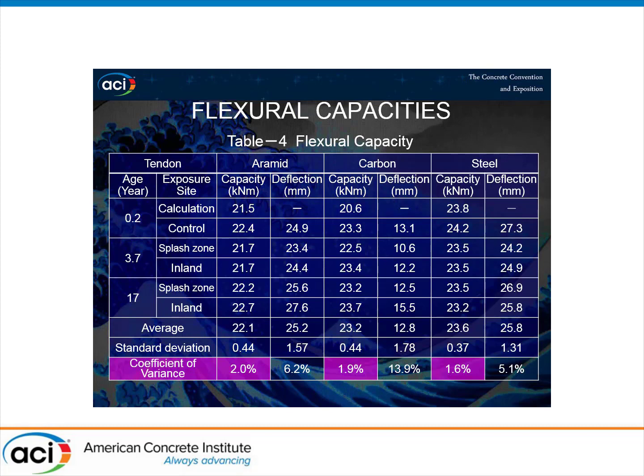To notice the flexural moment capacity, the values have no difference. They had a coefficient of variance less than 2%, and it matches nearly perfectly with the calculation. In other words, aging degradation caused by the sprays of seawater and temperature changes did not occur in 17 years.